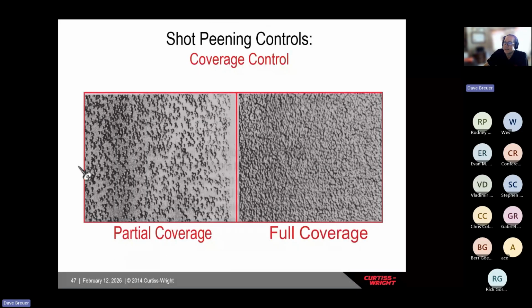And then the last thing is coverage. That would be what percentage of the surface area is obliterated by shot peening dimples. This is aluminum, a soft metal, so it's easy to see the dimples. You can see completely overlapping dimples, so this would be full coverage. Wherever you see the flat spots, you do not have coverage. So this might be 40% covered, if you will.